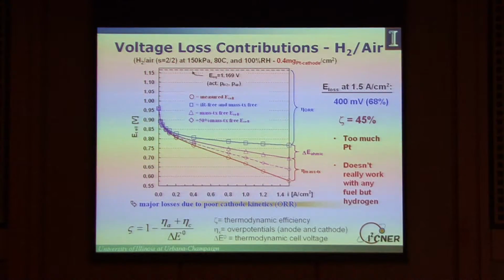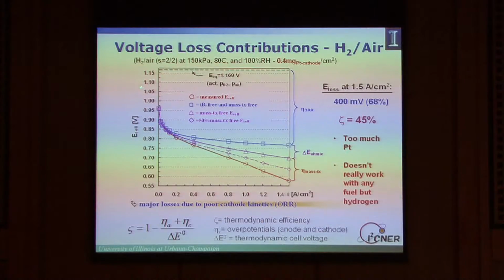Part of the reason, not the whole reason, but part of the reason is shown on this chart here. This is a chart of cell voltage versus current out of a real hydrogen air fuel cell. Now, the cell voltage right here is the difference between the two half cells. One of the half cells is, as I showed you, the hydrogen ion part, and that's running at, let's just call that 0. The other part is the oxygen-water couple, and that's up at around 1.2 volts or so. It's a little lower because we have less oxygen in the air.